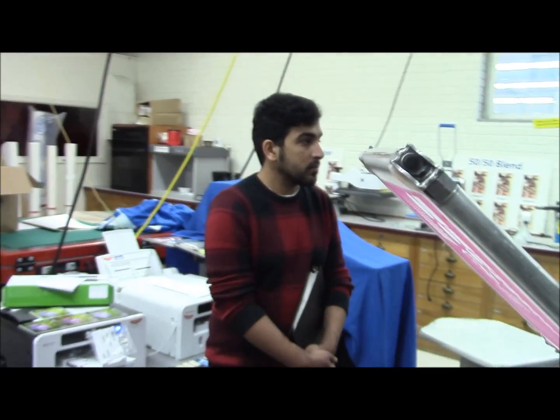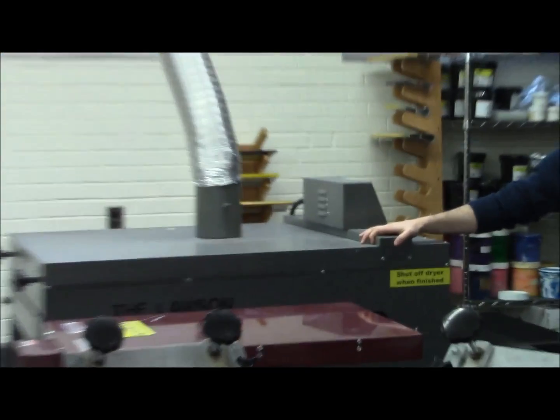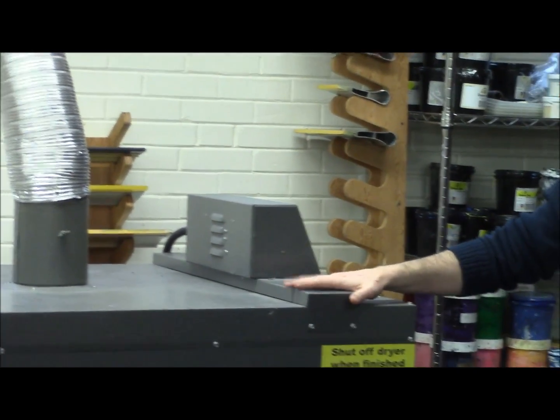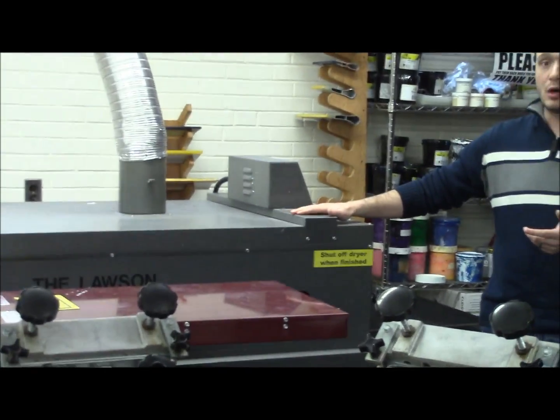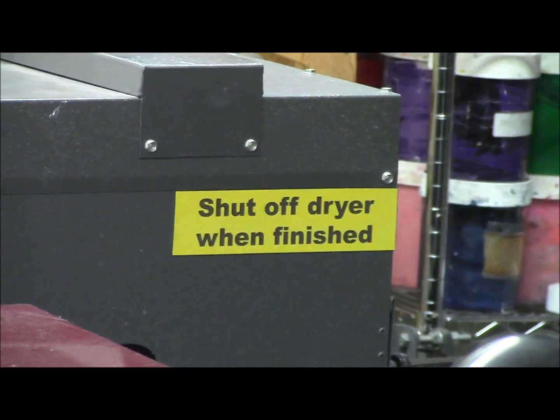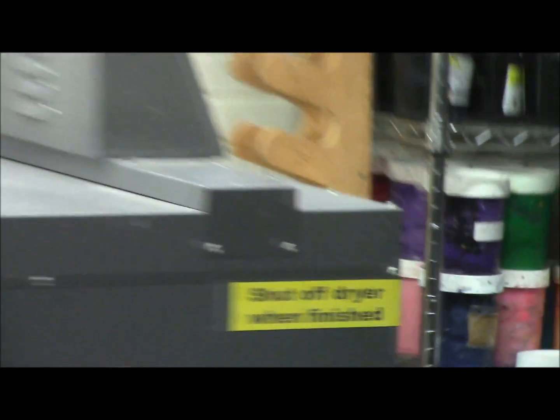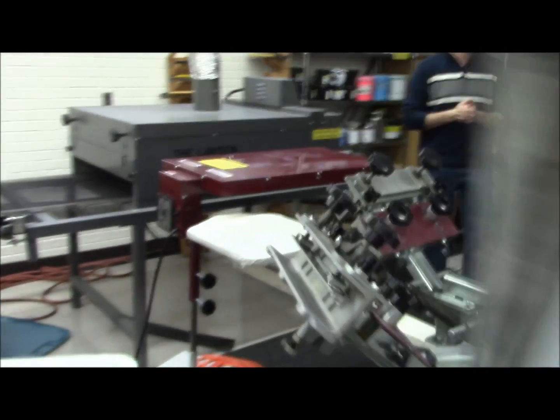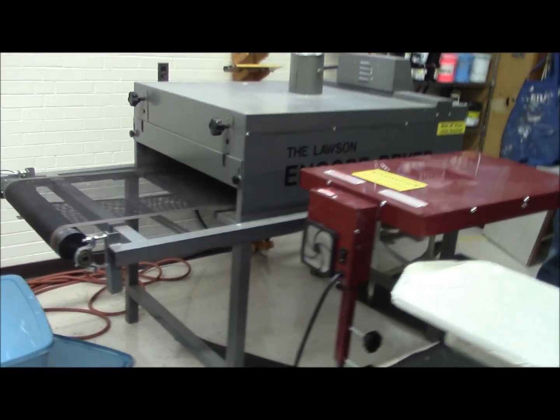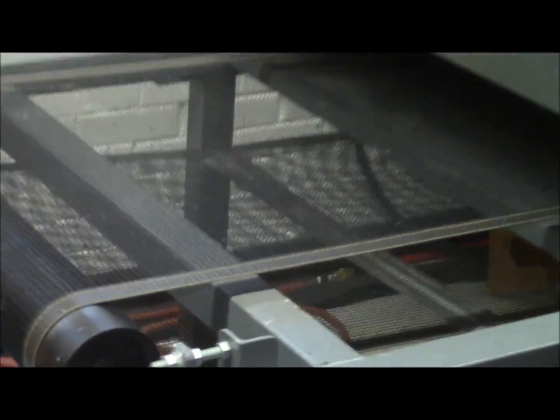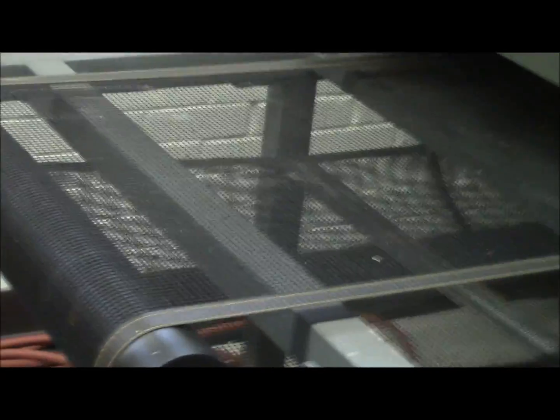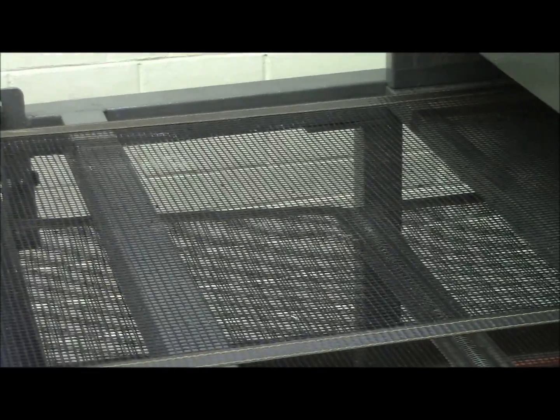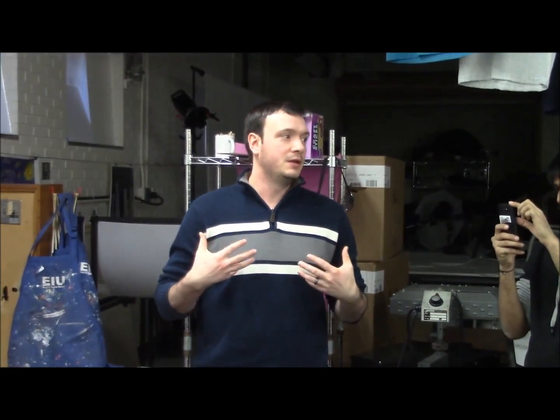So one of the other tools that we will have to be considerate of is, of course, the final curing unit, which is a belt dryer. On this belt dryer, we can adjust things like the temperature and also the speed at which the textiles will actually go through the dryer itself. And that's critical because if you have it going too slow through the dryer, you can burn or scorch the garment or actually overheat the inks that we use.